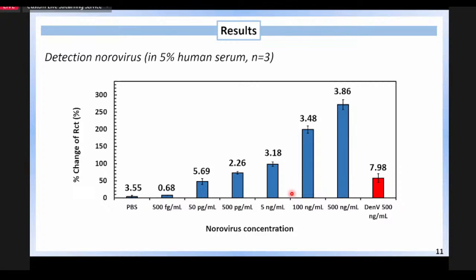checking the platform that I have fabricated by detecting the norovirus, and I'm immersing the norovirus sample in the human serum, and this is what we got. There is a very strong dose-dependent response. If we are increasing the virus concentration, the response also increases. While interestingly, if we change into the dengue virus, there's no significant interaction, indicating very high